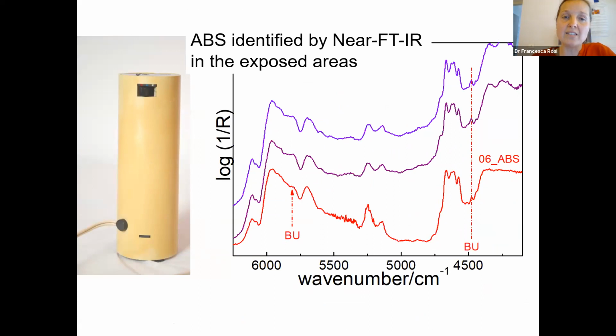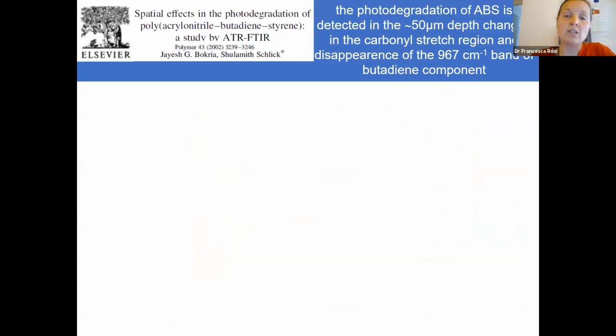We can explain this disagreement, taking into consideration the wide literature concerning the photodegradation of ABS, which affects the first layer of the material at the surface, and this can be monitored by looking at the decrease of the band of the butadiene component.